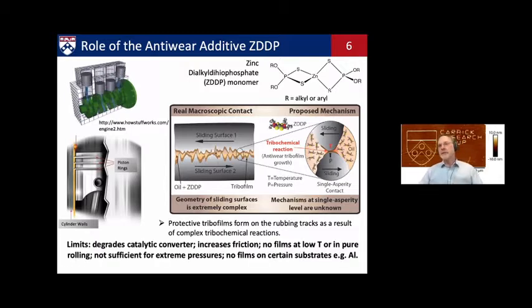So this has been used for decades, and it's extremely effective, and it's also a cheap molecule to produce. However, it has some issues. It degrades the catalytic converter due to the phosphorus and sulfur content. It actually increases friction a little bit. It also doesn't work if the temperature is too low or if you have pure rolling.